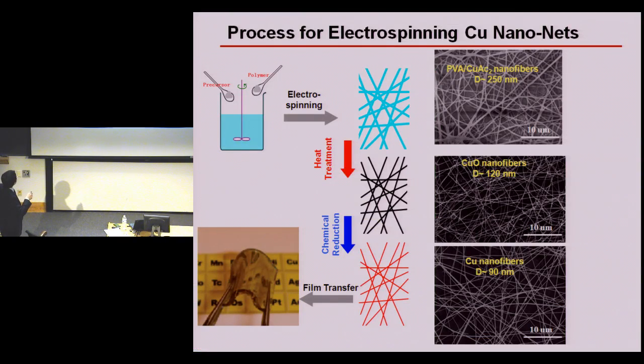So basically, we have copper acetate in a polymer solution with an inorganic solution. After the initial spinning process, we get these continuous fibers with junctions. After that, we burn the PVA fibers away, and then we get copper oxide. Then we reduce the copper oxide to copper in a hydrogen atmosphere. After that, we can transfer these copper nanowires onto different substrates so that we can fabricate devices.